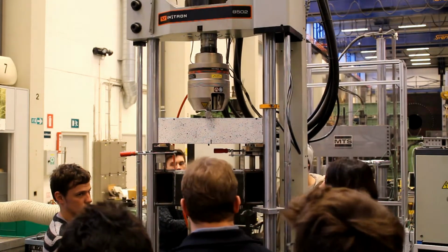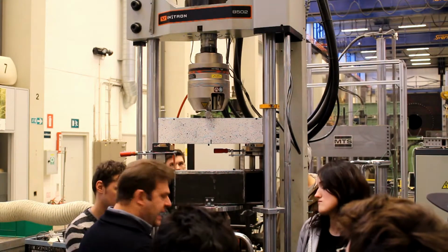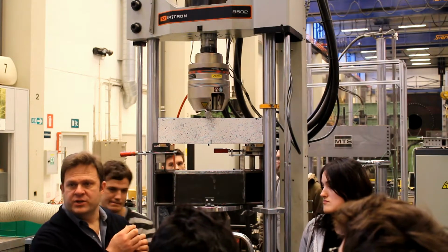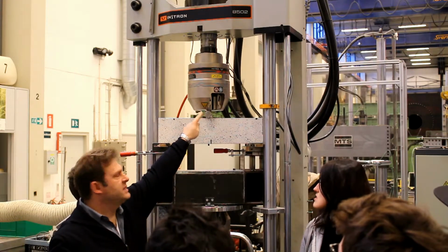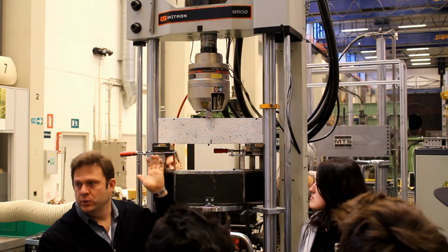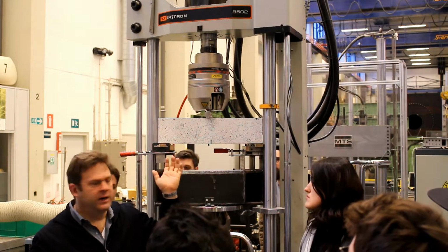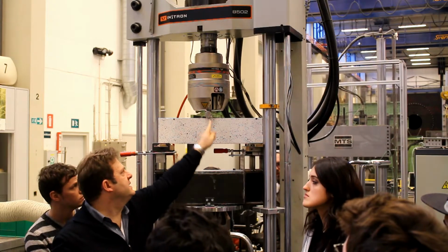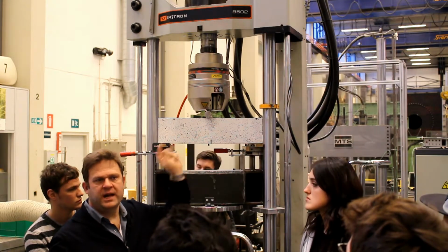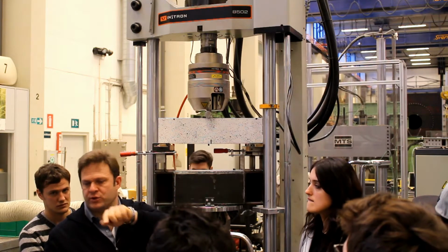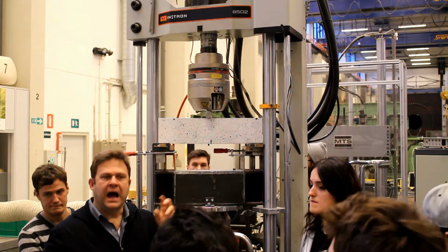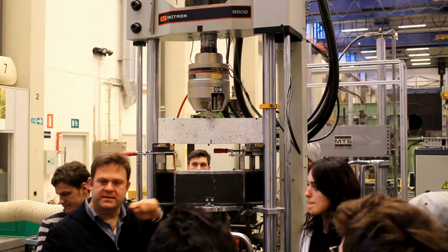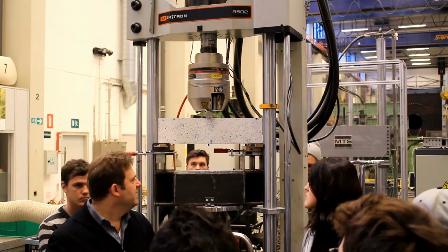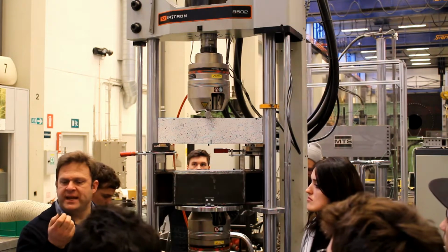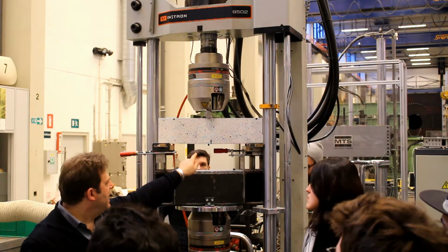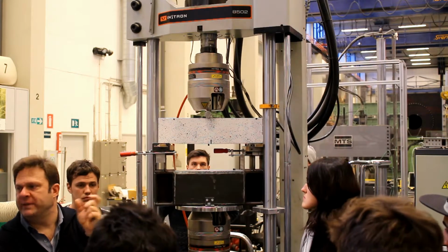So you can see now that unfortunately our device was lost. So now of course all we are left with is the displacement of the machine and the load. There is, however, a relationship between displacement, that is deflection of the beam, and the opening of the notch. You can also read that in the norm, how we can theoretically relate deflection to notch opening. But typically, we would want to maintain this measurement up to a crack opening of 3.5 millimeters.